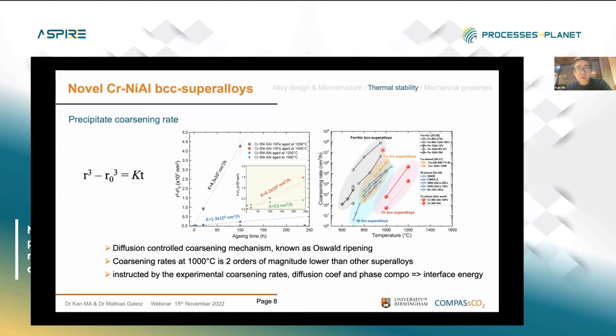So whether these precipitates are stable at high temperature, and whether they coarsen a lot. We have performed different aging at different temperatures for different times to study the coarsening kinetics of this material. We can see the evolution of the volume of the precipitates at different temperatures as a function of the aging time, and then we can determine their coarsening rate. And it's found that their coarsening mechanism is diffusion controlled.